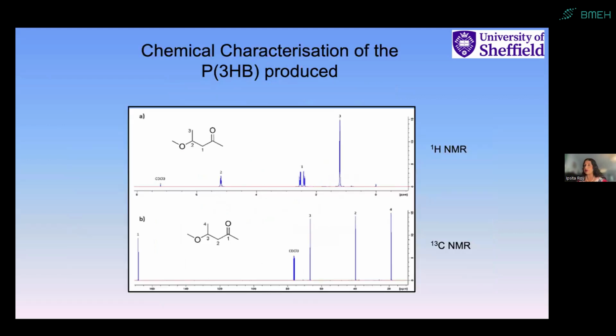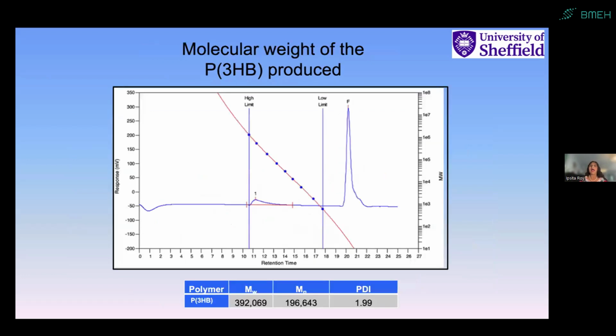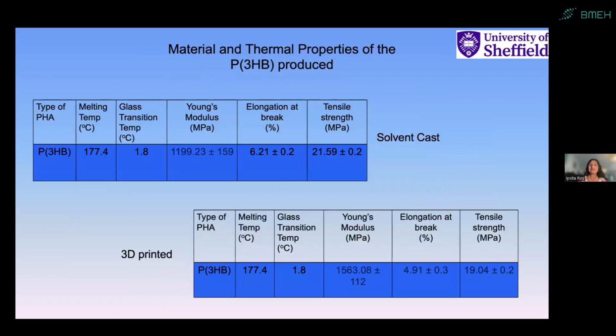After I produce the polymer, I always make sure we have the right structure. This is a C13 and a proton NMR of the polymer, and a GPC, which tells us the molecular weight of the polymer, because these are so crucial for the polymer to be used in biomedical applications. This is a typical example of P3HB that I produce in my group, and you can see that it is a high melting and a very stiff polymer. The Young's modulus is about 1,000 megapascal, or a gigapascal.